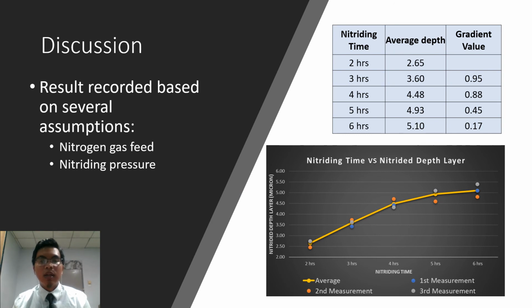It's highlighted that the recorded result is based on several assumptions. First of all is the nitrogen gas feed, and secondly is the nitriding pressure. The nitrogen gas feed could not be quantified in this project during the nitriding process because of the limitation of the nitriding equipment. Another thing is the nitriding pressure, which also could not be quantified and controlled due to the limitation of the equipment itself. It doesn't have the proper equipment to measure and control both of these parameters.